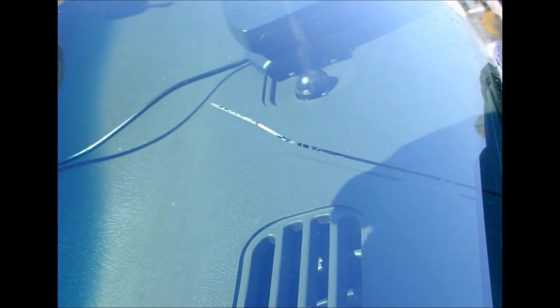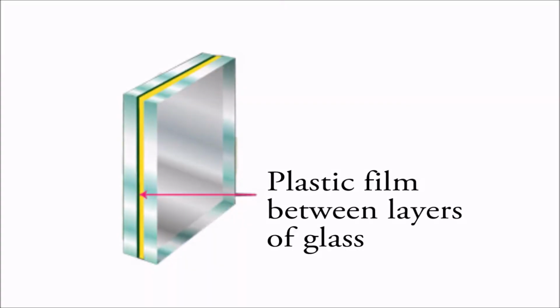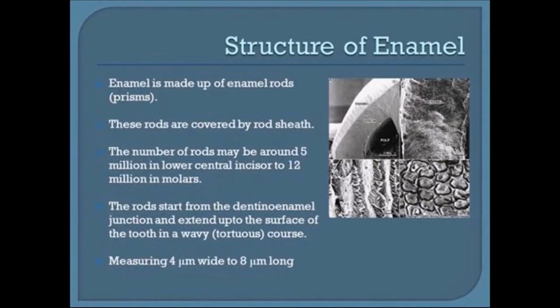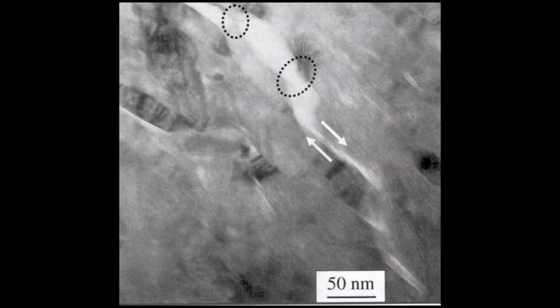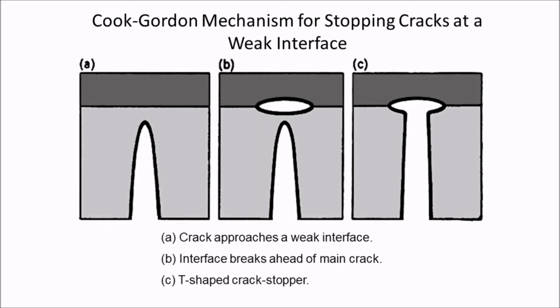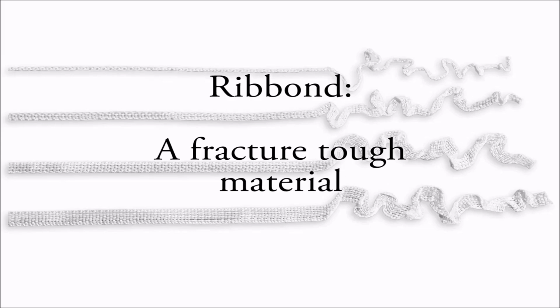A good example of this phenomenon is safety glass in windshields. A thin film of plastic is placed between the two panes of glass to act as a weak interface that redirects and blunts the energy of the crack from transferring from one sheet of glass to the other. Perhaps a more appropriate example of this phenomenon is tooth enamel. It is very common for tooth enamel to have cracks that have not propagated to a point in which the tooth has structurally failed. Each enamel prism is surrounded by a protein sheath. These protein sheaths create relatively weak bonded interfaces between the enamel prisms. These relatively weak interfaces blunt and redirect cracks, making the enamel fracture tough. If there was a strong bond of one enamel prism to the next, the tooth enamel would be brittle and our teeth would shatter with relative ease. Ribbond, a fracture-tough material.